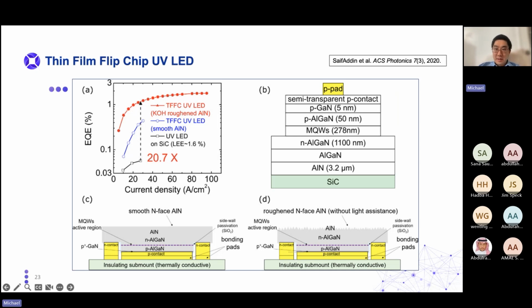So this is the epitaxial film stack. Because silicon carbide and aluminum nitride are closer in lattice constant, you can grow much thicker material and still not crack the material.